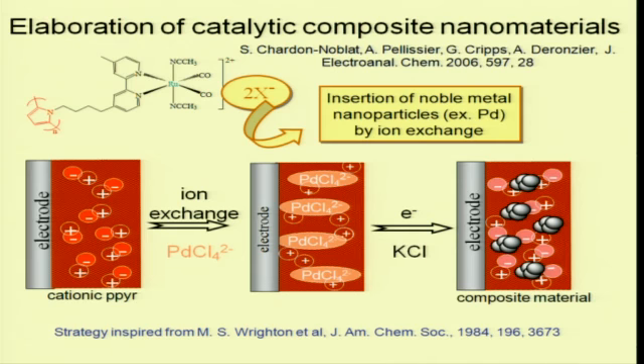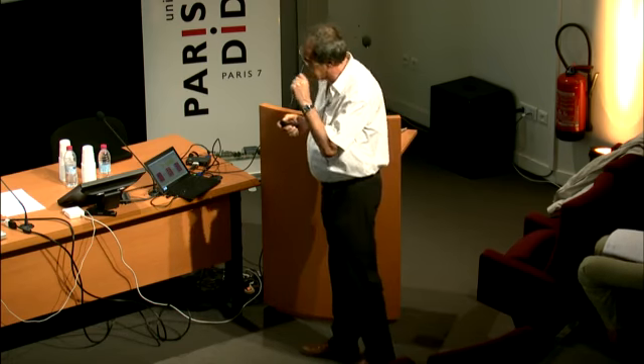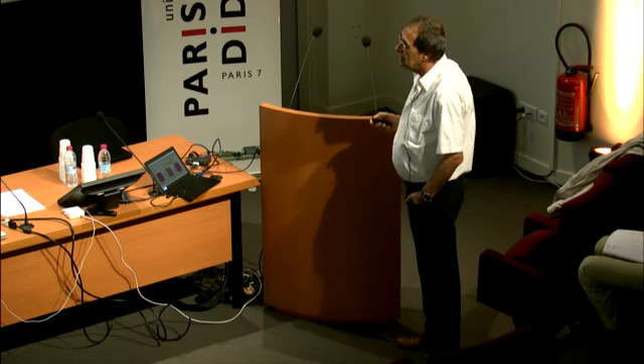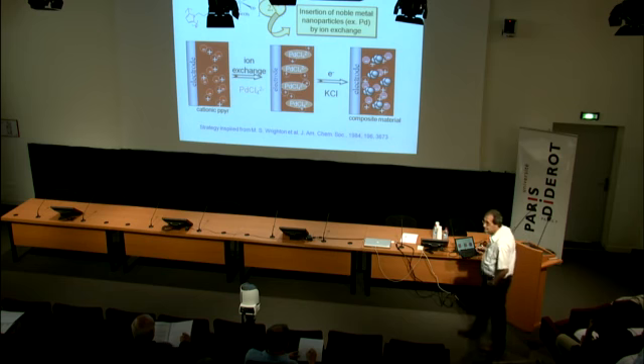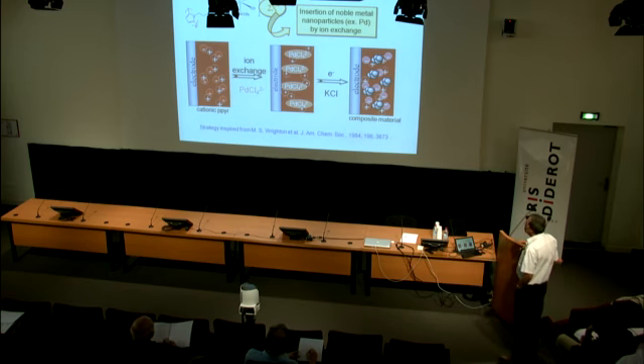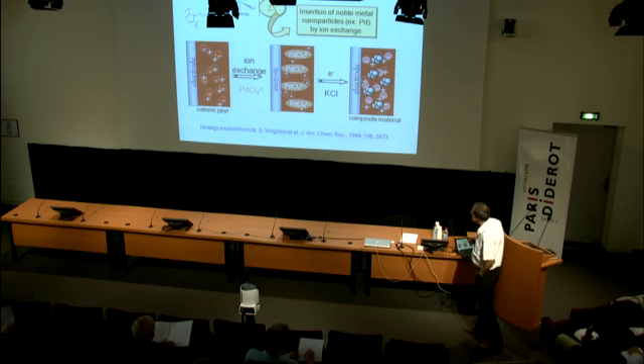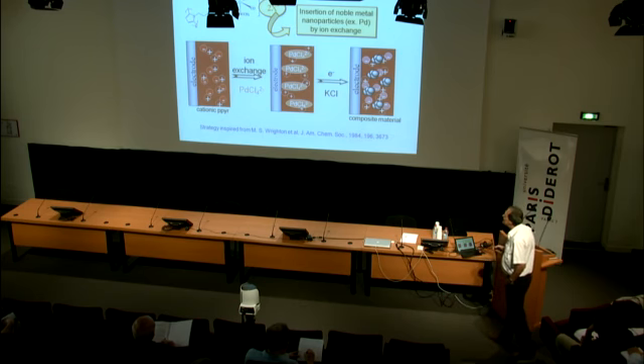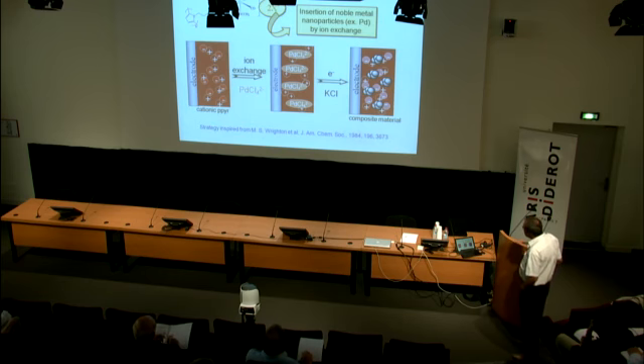So how did we make that? We used the strategy developed by Wrighton, as I showed you at the beginning with the viologen with palladium. The idea was very simple. We use a polypyrrole film in which the ancillary ligands are acetonitrile instead of chloro. Why? Because the film is positively charged. And what happens if you put this kind of modified electrode in a solution containing, for instance, this anionic complex of noble metal? We replace the initial anion in the film by this palladium chloride, for instance. And if you reduce the system in situ, you make a composite material of the polymer film with particles.